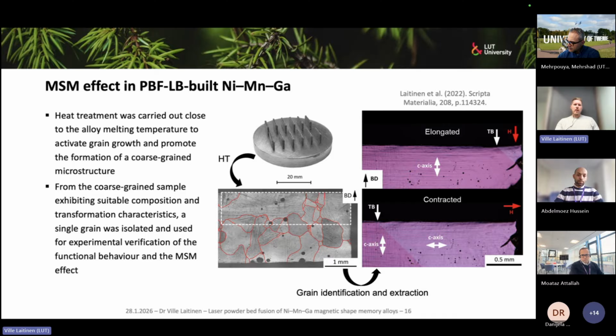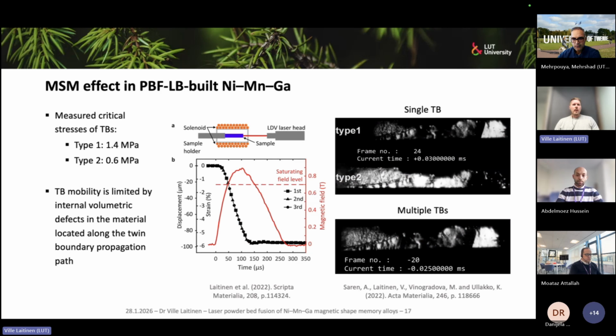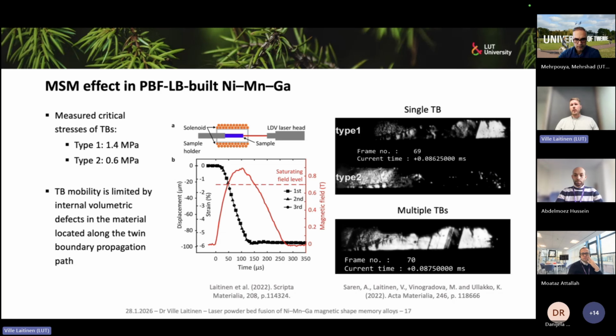And when we have this grain coarsening, then we could select an area where we could extract the grain for actual testing. So we can actually know, does this material itself have such a defect structure that it would actuate, or would it not actuate? And in this material, we could actually make almost full strain. So we can get this 5.8% magnetic field induced strain, which is, with this particular alloy, the theoretical maximum strain is around 6%. So it's nearly maximum theoretical strain.